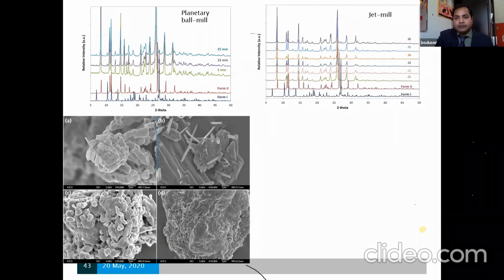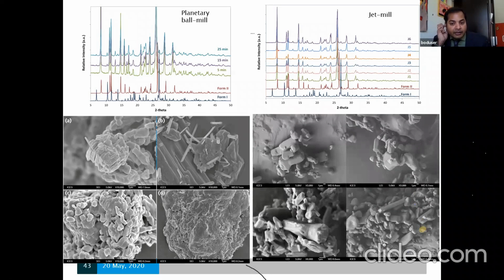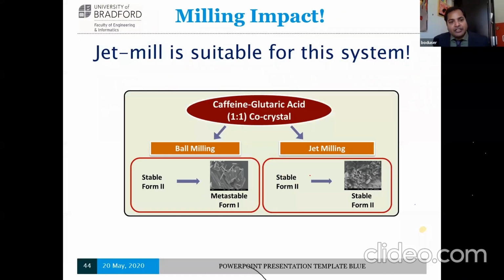So this is a jet mill sample. In the jet mill sample, we have conducted various grinding pressures and also injection times. In all the tested conditions, what we have found was there is no appreciable physical change, which is a very good sign. In the SEM images, scanning electron microscopy images, in all of these, particle size distribution is changing. Particle sizes are getting finer, which is useful, but there are no physicochemical changes. So this is ideal. To summarize this work, jet mill is suitable for this particular system.